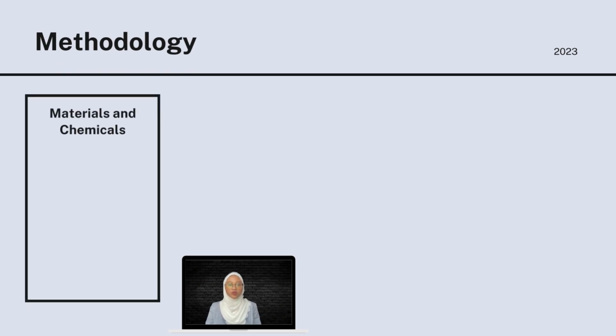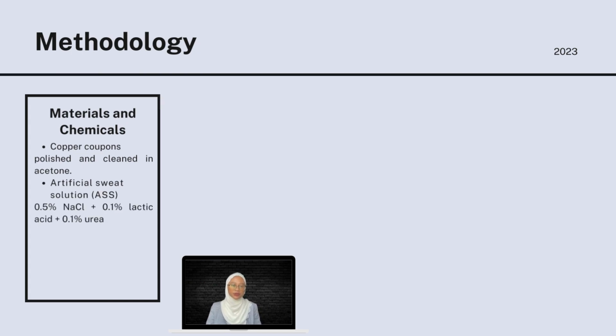Now, we move on to the methodology of this study. The materials and chemicals used are copper coupons, which were polished using silicon carbide paper and then cleaned in acetone. Next is the artificial sweat solution, which was made up of 0.5% sodium chloride, 0.1% lactic acid, and 0.1% urea, made for 100 ml before adjusting the pH to around 6.5.